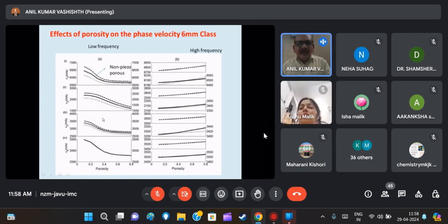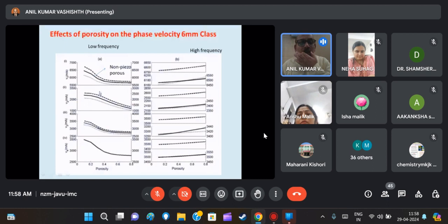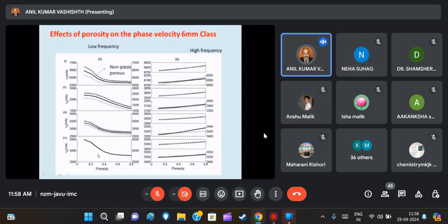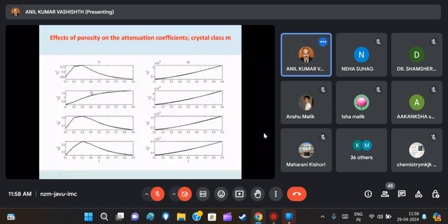So in this range, we can see there is a great appreciable change, variation in the velocities of the waves which propagate in such smart materials, and the change up to the range of 30% is very appreciable. So the results were motivating and encouraging to go ahead with this model. Then we presented how the porosity will affect the most general class, that is the crystal class of M, when there is symmetry only in one coordinate plane.